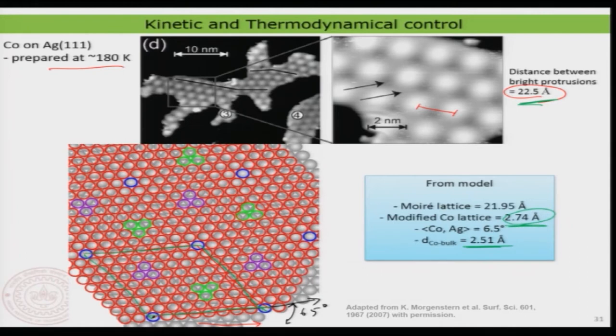So that's quite striking. Why is it striking? Because now you can see, to generate this model, I need to relax the cobalt atoms farther apart with respect to each other. In the previous case, you recollect, I had to compress slightly the distance between the cobalt atoms. But in this particular case, I need to basically just relax the cobalt-cobalt distance in order to get the microscopic arrangement correct, as well as the agreement with the experimental data. So this is quite striking, right?